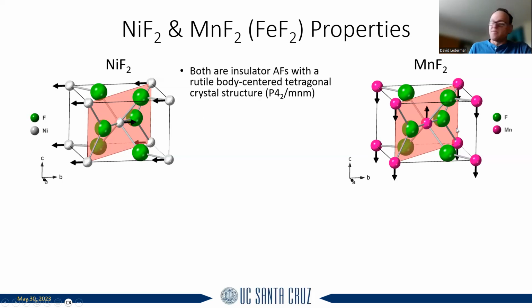And again, I just want to very briefly go over what the properties of these materials are. Both nickel fluoride and manganese fluoride are insulating antiferromagnets. They have a rutile body-centered tetragonal crystal structure. And just for those of you that don't know, rutile is a form of titanium dioxide. That's just the name of the crystal. In titanium dioxide, you have titanium at the corners here, and then you have oxygen. For these materials, these are the transition metal, in this case, manganese or nickel. And these green spheres here are the fluorine atoms. Okay. And when you take manganese fluoride or iron fluoride, which has an even larger uniaxial anisotropy, it has a huge uniaxial anisotropy along the c-axis. This is the c-axis in this direction.